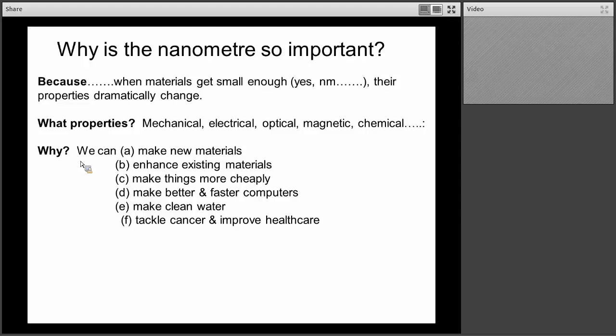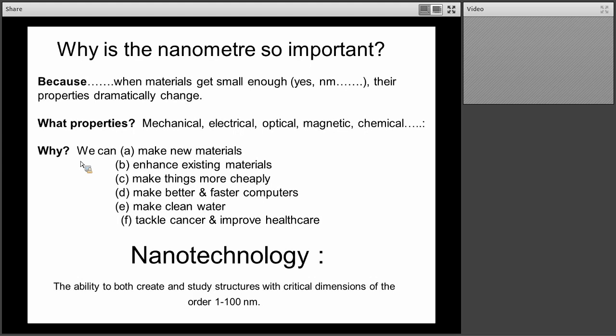So why is the nanometer such an important length scale? The main reason is that it relates to the length scales associated with many properties of materials — specifically mechanical lengths, so length scales over which strain is felt, electronic mean free path, optical skin depth, magnetic exchange length, and chemical bond lengths. These are all typically in the range of a few fractions of a nanometer to a few tens of nanometers. Once you pattern materials at these length scales, you start to be able to tailor the way those materials behave, and it becomes very dependent on the geometry. The safest definition of nanotechnology I use is the ability to both create and study structures with critical dimensions of the order 1 to 100 nanometers — and that's exactly the length scale at which scanning probe techniques come to the fore.